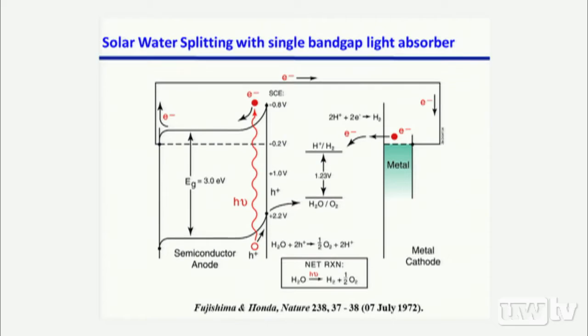And for artificial photosynthesis, or more specifically, solar water splitting, the first example came out of Fujishima and Honda's group, back in the 70s. In this first example, they utilized TiO2, titanium oxide, to drive the water splitting. The reason they used TiO2, a UV material, is that TiO2 will give you enough photovoltage to drive those two half reactions.